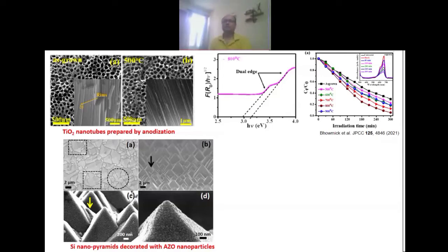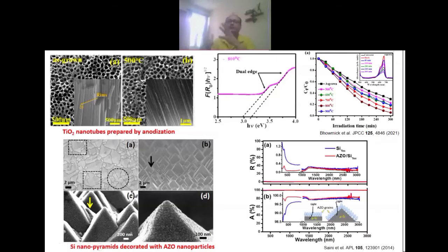So how do we find out whether it's metallic or semi-metallic in nature? You can see that here is the semi-continuum state. If we give temperature, then electrons can go to the free electron part, the free space where states are available. So they can conduct, and they can also scatter. If you increase the temperature, then scattering will increase, and then the resistivity increases. So for a conductor, like a metal, the resistivity versus temperature is always increasing.